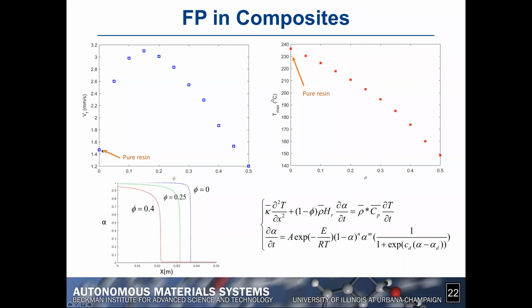Phi equals 0 corresponds to the pure resin case. And what we obtain using the model is that as we increase phi, the speed of the front will start by increasing, reach a maximum, and eventually start to decrease afterwards. If we look at the evolution of the maximum temperature, we can see a steady decrease in the maximum temperature behind the front. The bottom left figure shows a snapshot of what the front looks like for 3 different values of the fiber volume fraction, from 0 to 0.25 to 0.4.